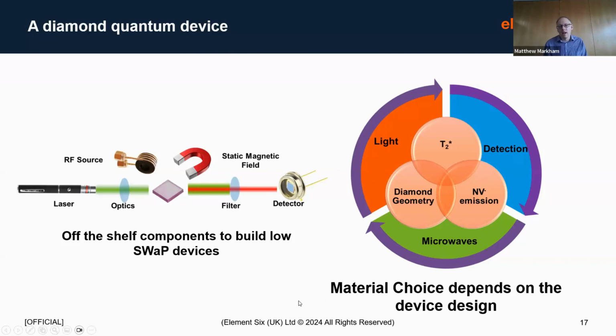On the right here, I talk about how the material choice depends on the device design. So in the center, I've got three properties that relate to the diamond. T2 star, this is the spin lifetime of the NV defect, so you want that to be as long as possible. NV minus emissions, that's the light coming from the defect of interest. You want that to be maximized, whilst the other red luminescence is minimized. And the diamond geometry, so how the light is going to bounce around the diamond, and how the light's going to be extracted from the diamond.